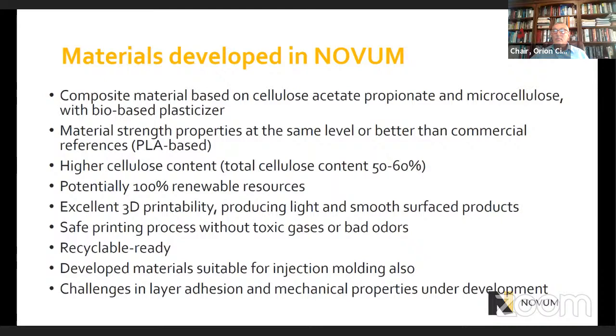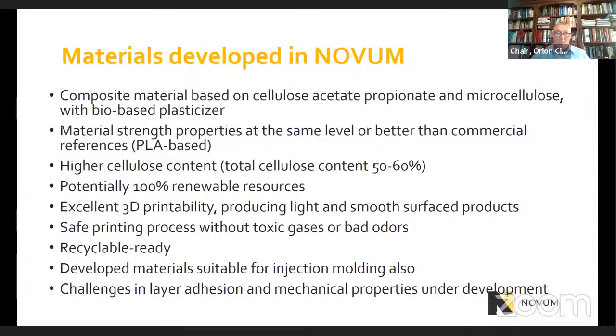They have demonstrated excellent 3D printability, producing light and smooth surfaces in the products. And the printing process is safe. There is no gas or bad odors generated if the moisture content of the material is below a certain limit. These materials are recycling ready, meaning that after printing, the components can be crushed and granulated and printed as such again. And we have studied that the material properties are not deteriorating up to 8 cycles. And these developed materials are also suitable for injection molding, which extends the possibilities for their use. We have faced some challenges in layer adhesion and required mechanical properties for certain end-use applications, but these are now being considered in the project.